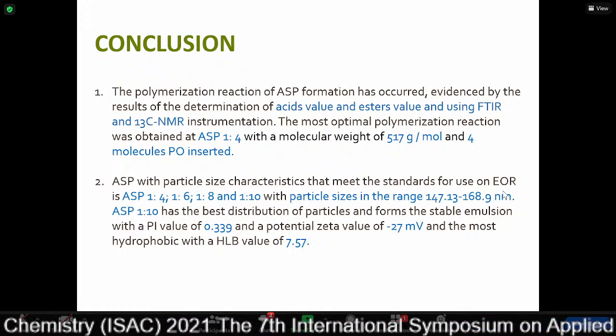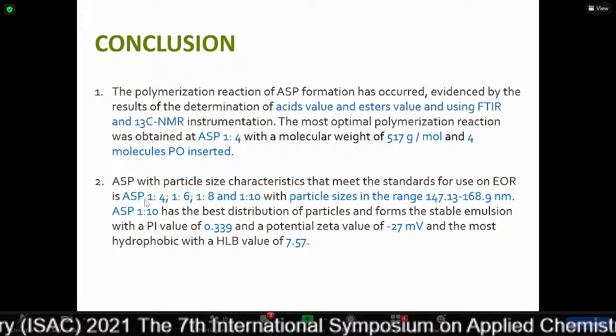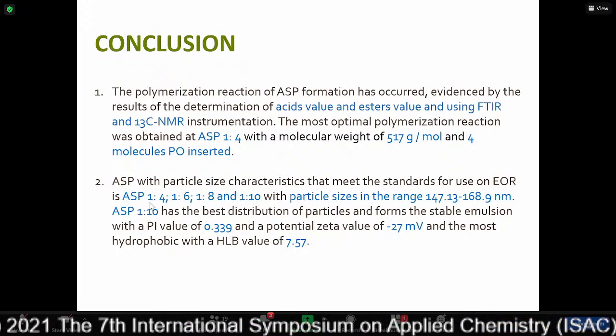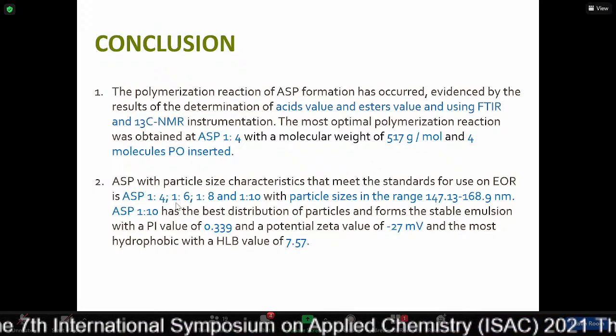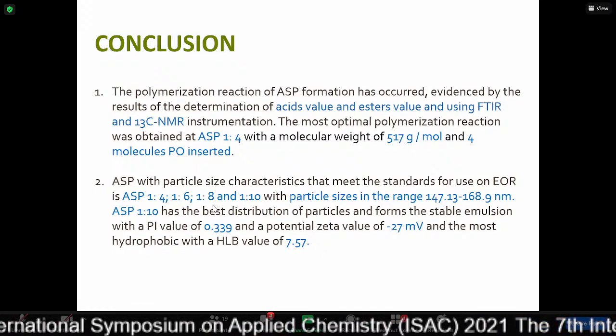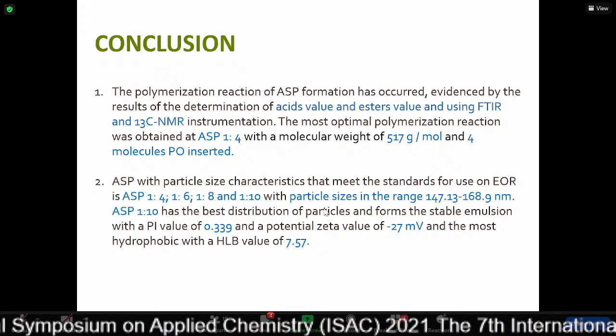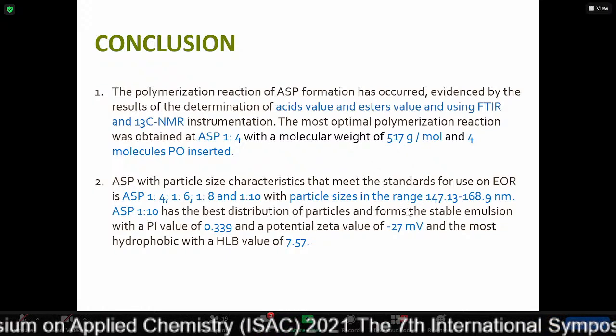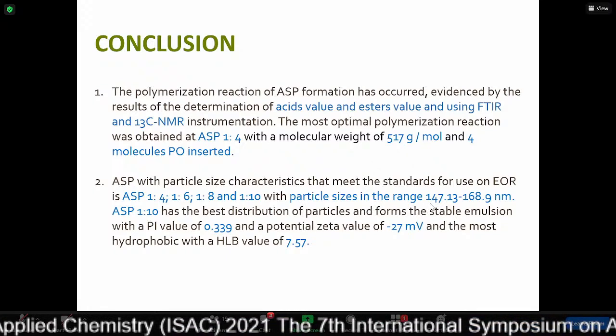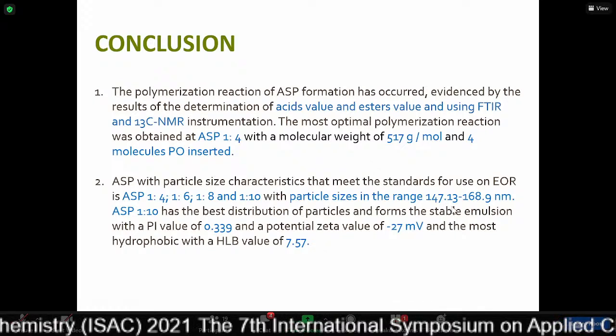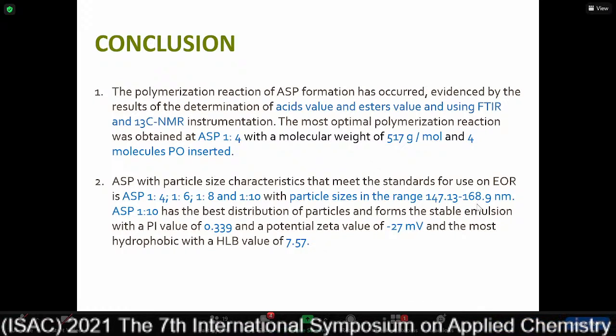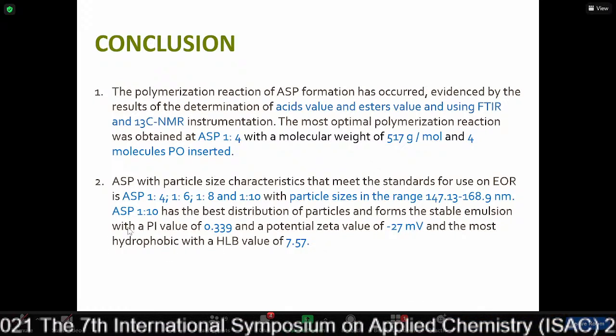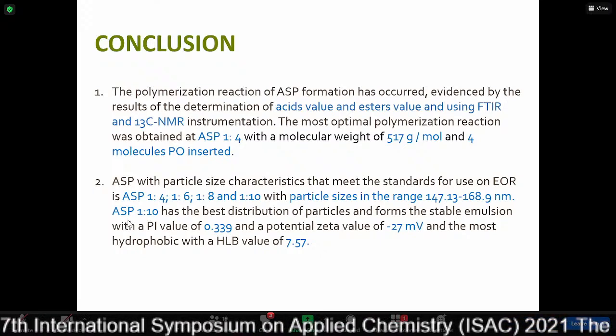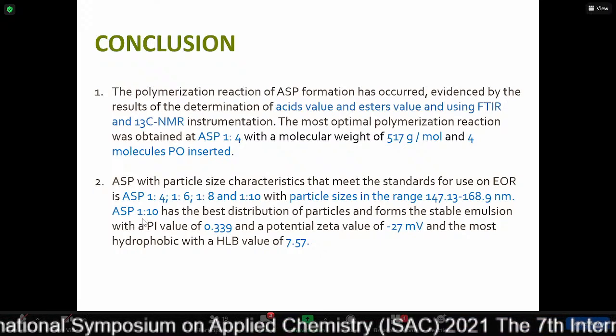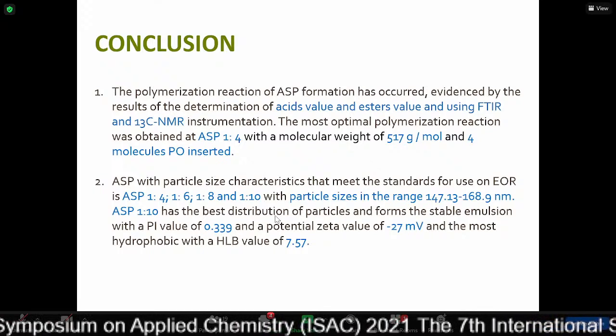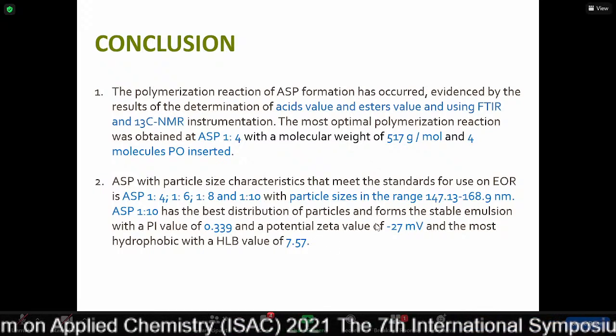Stearic acid propoxylation with particle size characteristics that meet the standard for use in EOR, enhanced oil recovery, is the first formula 1:4, 1:6, 1:8, and 1:10, with particle size in the range between 140 and 160 nanometers.